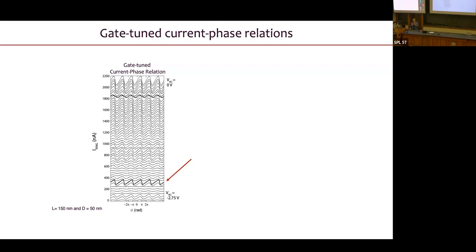Then as we change the gate voltage, we start to get a current phase relation that indicates a small amount of superconductivity, the magnitude you'd expect to be associated with a single mode, given what we know about the gap of this material, starting to flow through the ring. You can see that in some cases it looks pretty sinusoidal, and in other cases it has this very skewed shape. And then weirdly, at some places, it gets this backward skewed shape.